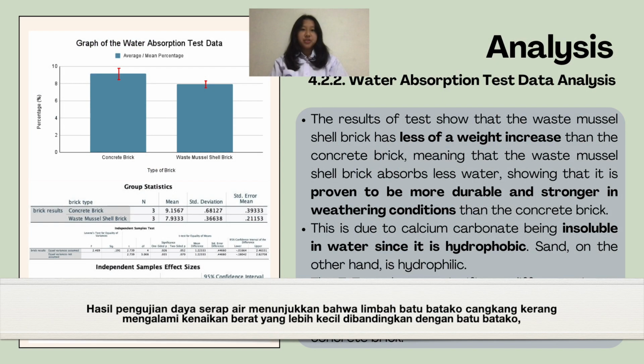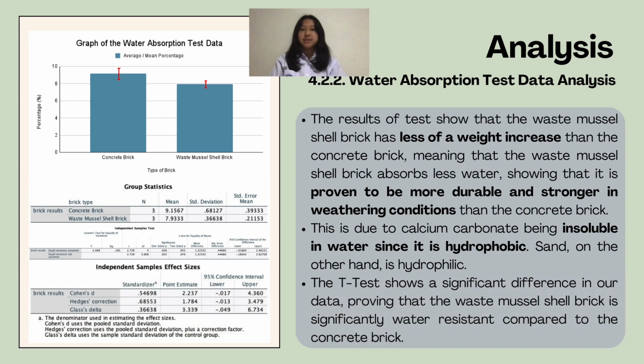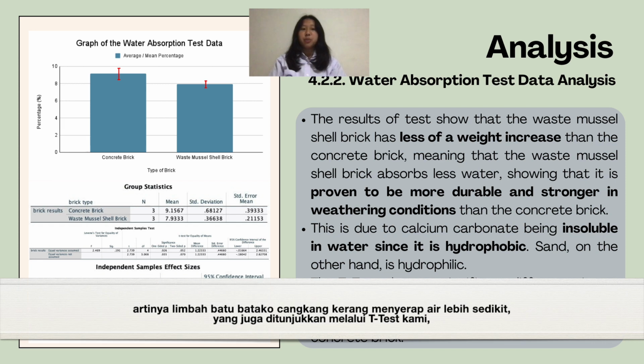molecules. The results of the water absorption test shows that the waste mussel shell bricks has less of a weight increase than the concrete bricks, meaning that the waste mussel shell bricks absorbs less water, which is also seen through our t-test, thus proving it to be much more durable and stronger in weathering conditions. This is due to the calcium carbonate found in the waste mussel shells, being insoluble in water since it is hydrophobic, meaning it repels water.